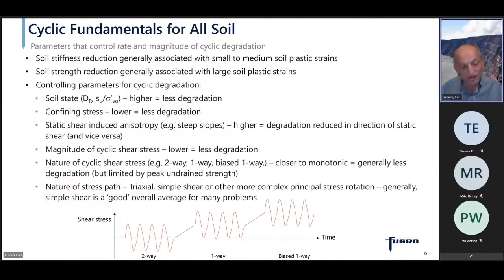The magnitude of cyclic shear stress, fairly self-evidently lower, is always going to be less degradation. The nature of the cyclic shear stress, so we can have two-way, one-way, one-way bias, which are illustrated on the bottom. So two-way is where we're cycling plus or minus equal values. One-way is where we're cycling from a positive value to zero. And then biased is where we have an increasingly offset, so the lowest value is not going down to zero. And generally speaking, the closer we move from the two-way to the biased one-way, the less degradation we will get.